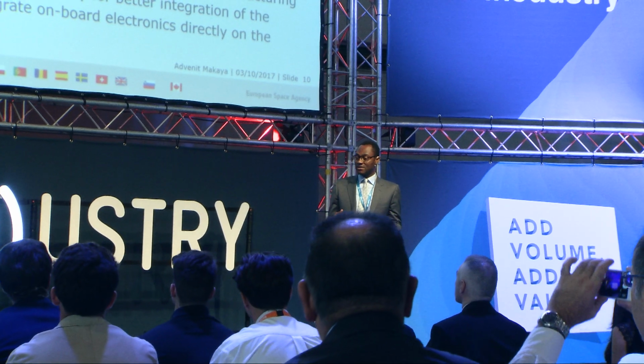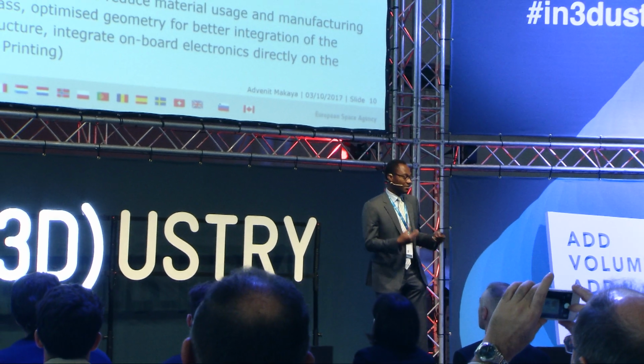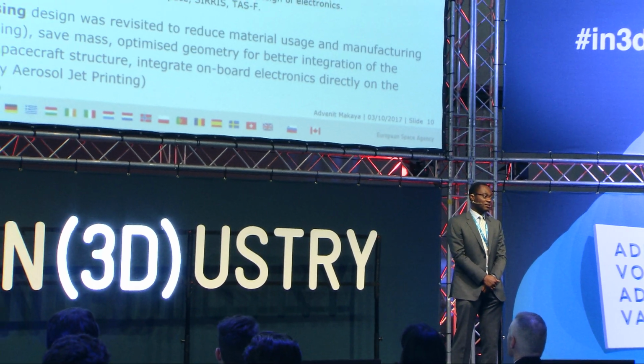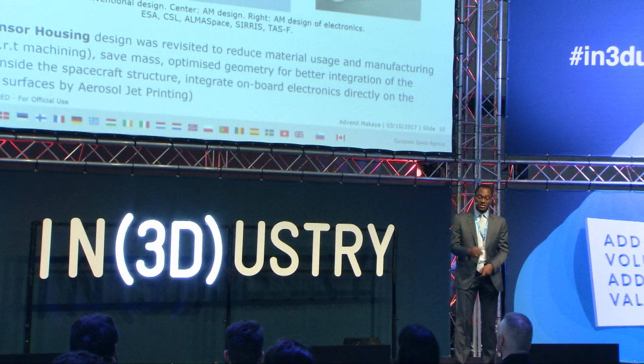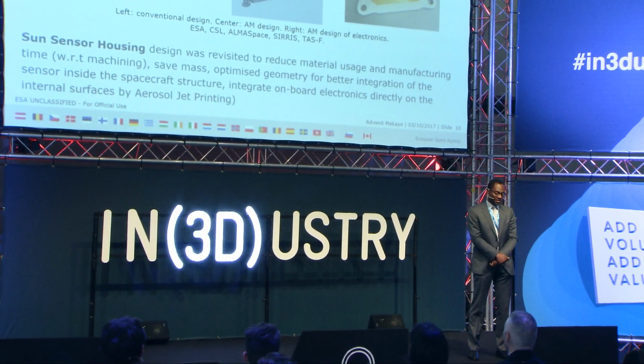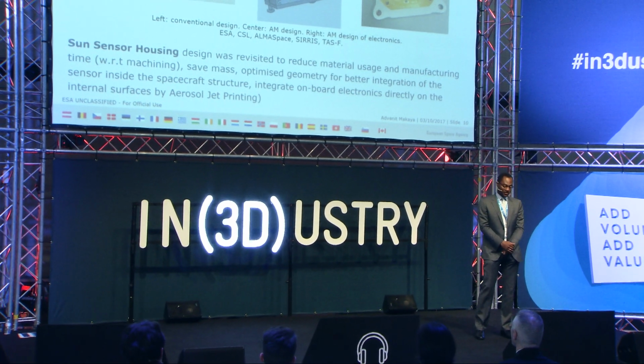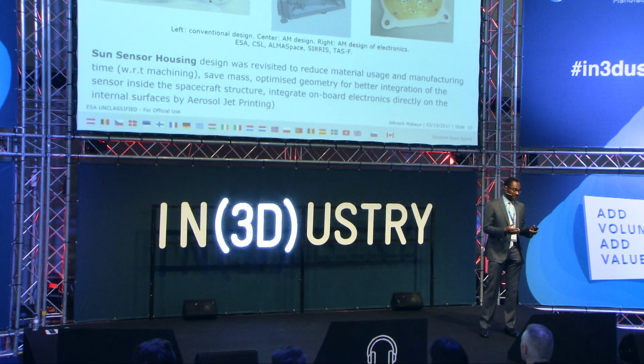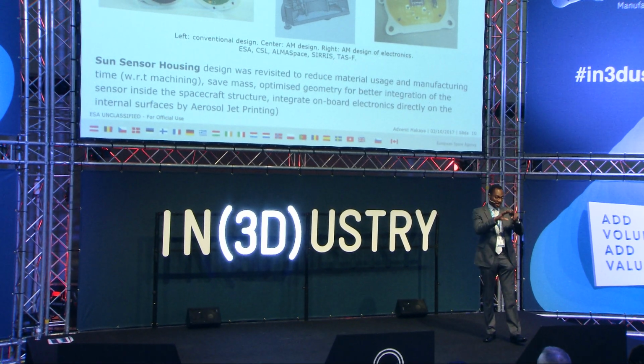So based on these preliminary studies, we ramped up the complexity and the collaboration with industry in order to demonstrate some products which use the principle of designing for additive. This is also a part which is exhibited here. It's a sensor where we optimized the volume and the mass of the casing of the sensor by using selective laser melting in this case. And we replaced the printed circuit board by printing directly the tracks onto the base plate using aerosol jet printing. It was not completely successful, but it's a demonstration of the feasibility of additive to reduce the complexity of a part.